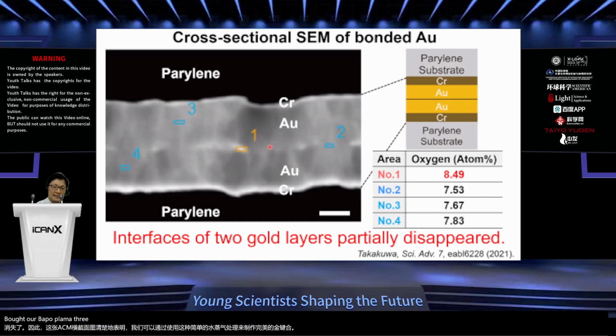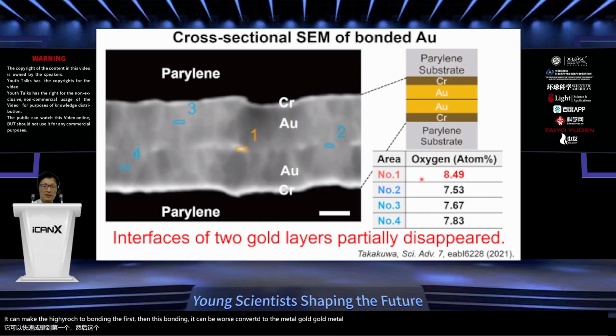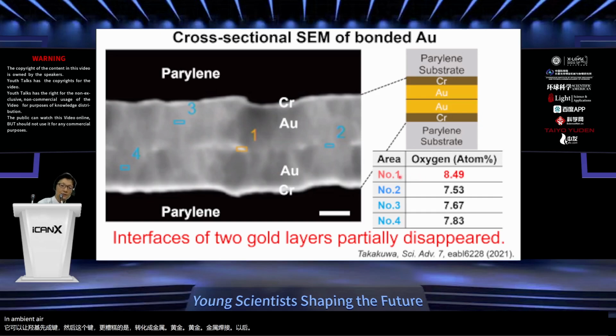And we performed EDX analysis of this interface region and the bulk gold regions. We observe that this interface, this white region, implies a slightly increased oxygen amount. So we guess that the generated OH groups can make hydroxyl bonding first. Then this bonding was converted to gold metal bonding later in ambient air conditions.